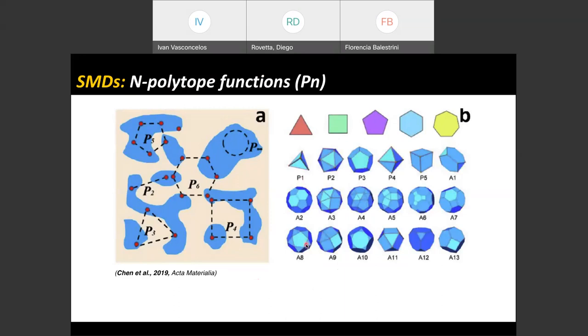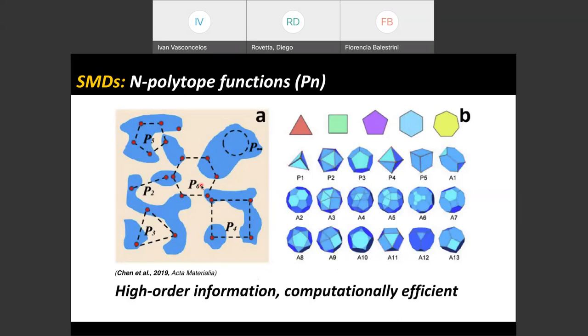When we pick these fixed shapes with orientations and vertices, what happens is that we can check the probability that the vertices fall or do not fall in a single phase. Because they're fixed shape and orientation, to scale them takes only a single parameter. So we can change the size of these and scale them with a single parameter. That means that computing these is just as efficient as computing a two-point correlation function. Now, are these useful in high-order correlations?